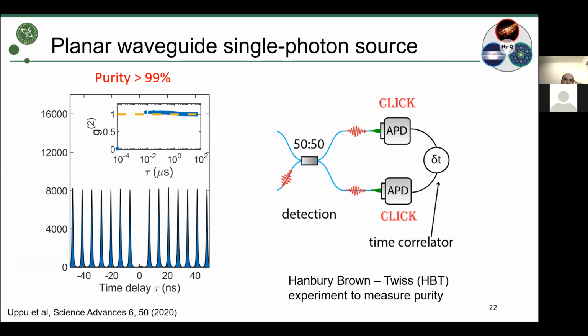So how do we quantify the quality of the single photon sources? Basically, we do the experiments that I already mentioned. The first one is technically called the Hanbury Brown and Twiss experiment. So you send a single photon to a 50-50 beam splitter, you try to split the photon, and you put 2 detectors at the output. If it's a true single photon source, the 2 detectors should never click simultaneously. So if you take a correlation between these photodetectors, what you should observe is that at 0 time delay, there are no clicks. And that's exactly what you see here in this data.